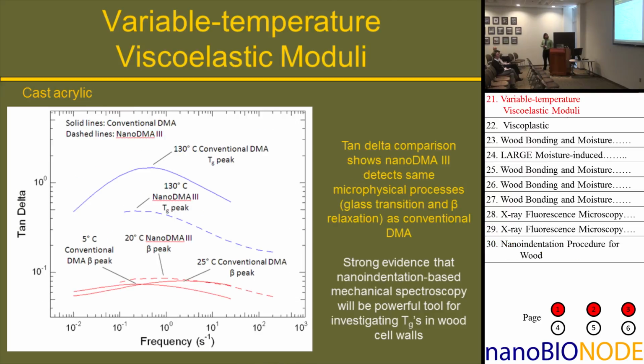conventional DMA. And then also, if you look at the tan delta, you can see that the peaks line up pretty well. And so on this cast acrylic in the conventional DMA, we saw a peak at less than 1 hertz, and we see that same peak in the nano DMA. And then the peak related to the beta peak in the conventional analysis showed up the same place you'd expect. The nanoindentation showed up the same place it showed up in the conventional measurements. So this is really strong evidence that we can use nanoindentation-based mechanical spectroscopy to investigate glass transitions in wood cell walls, which I'm going to show later, that there's a moisture-induced glass transition in the hemicelluloses that we can actually detect with nanoindentation.